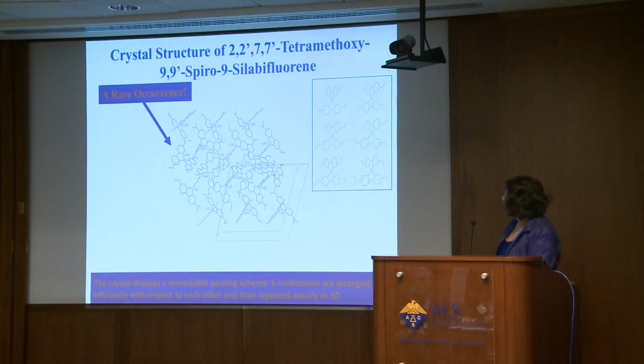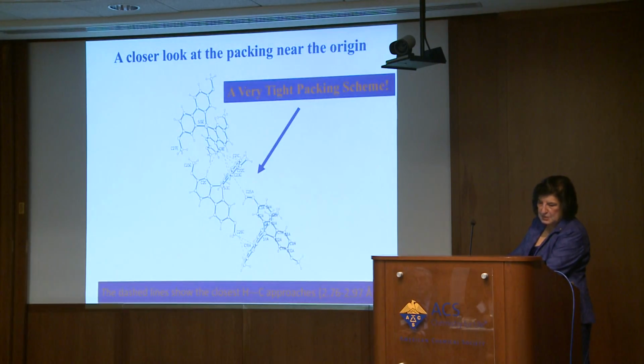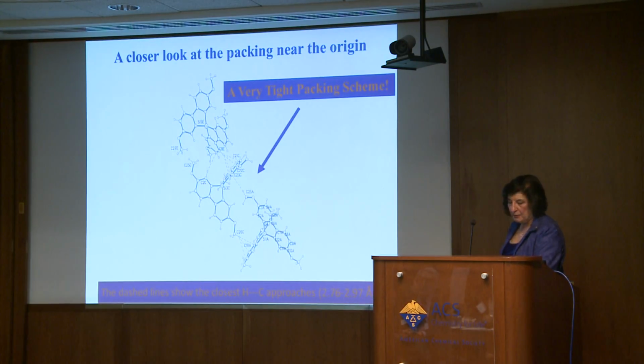Well, we did some characterization of the crystal structure as well. We grew a single crystal of these molecules, and this is interesting because the crystal displays a remarkable packing scheme, and you have 6 different kinds of conformers that are arranged in a very efficient way. This is a closer look at the packing, which shows a very tight scheme, and you get very close hydrogen to carbon contacts. You know, these are very small numbers for this type of interaction.